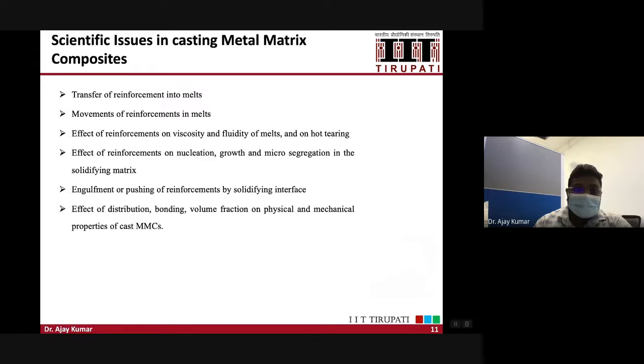So when you make composite materials using conventional methods, for example, metal casting, casting is a very well-known method, and there are scientific issues when you use casting for making these MMCs. The first issue is the transfer of reinforcement into the melts, then movement of reinforcement in the melts, effect of reinforcement on viscosity and fluidity of melts, effect of reinforcement on nucleation, growth and microsegregation, then engulfment or pushing of the reinforcement particles by the solidifying interface, and then the effect of distribution, bonding, and volume fraction on physical and mechanical properties of MMC. So these are the scientific issues. These issues are still there, and it has a lot of scope for research to address them.